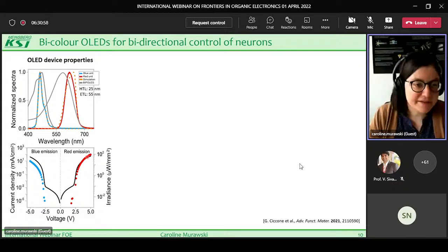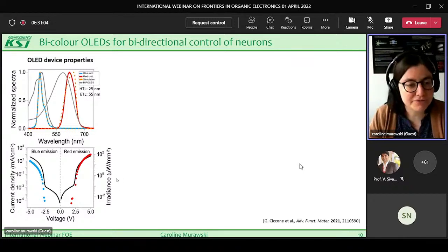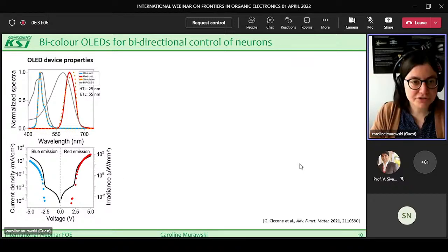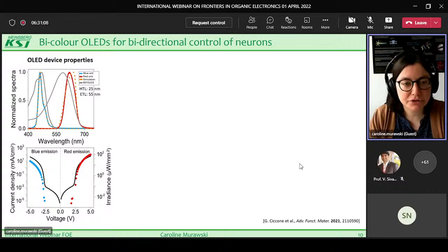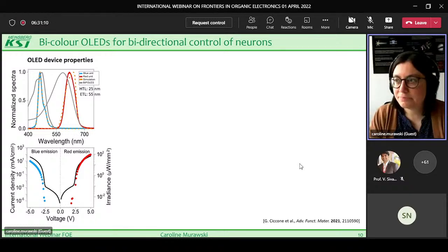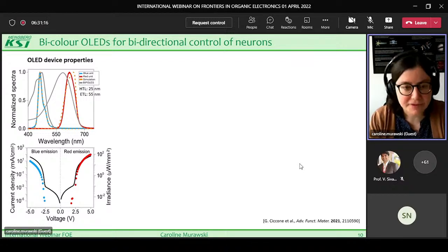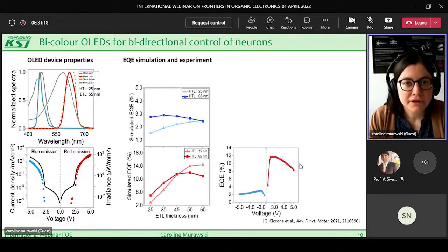The irradiance is somewhat lower in these devices, reaching approximately 100 microwatt per square millimeter. The main reason is that these devices were pretty large area, I believe around 18 by 18 millimeter square.